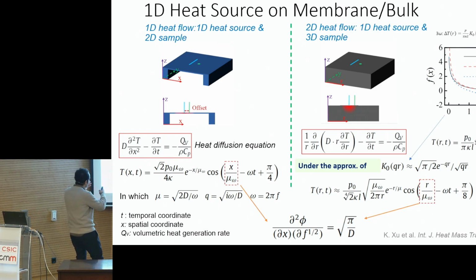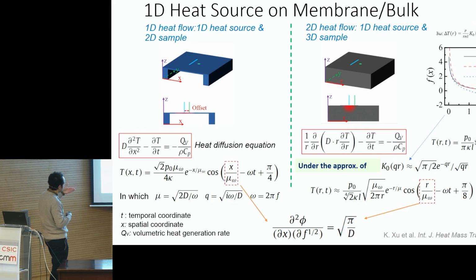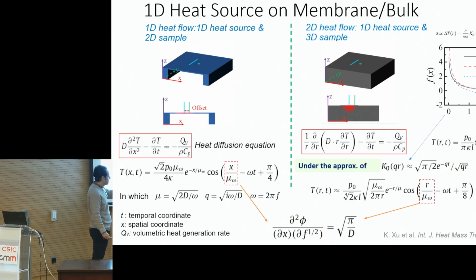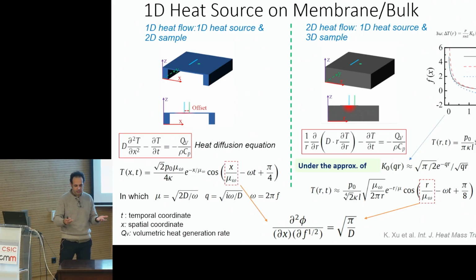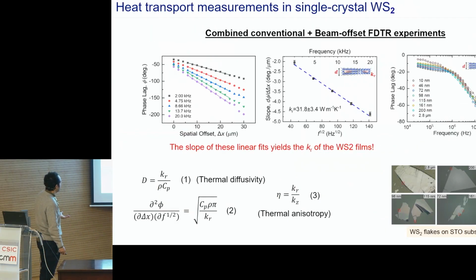Finally, starting from the heat diffusion equation, we end up with an expression where we have the second derivative of the phase lag that we measure with respect to the position, at a given modulation frequency, and from it we can extract the thermal diffusivity of our material. And then from there, we can extract the in-plane thermal conductivity, since we know the heat capacity and the density of our material. So these are the experimental data: the phase lag as a function of the spatial offset, and the slope of these linear fits gives us the in-plane thermal conductivity.